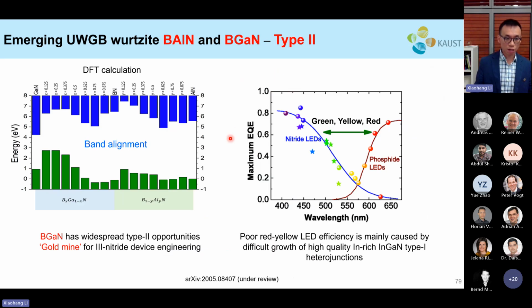So in addition to BAlN, we also look at how BGaN and BAlN with other boron compositions have in terms of the type 2 opportunities. As you can see here, this is the DFT calculation of the band alignment for BAlN and BGaN. This is gallium nitride and this is aluminum nitride, those two are well known, right? But when you add boron into the GaN and AlN, you start to see that the band alignment starts to change pretty dramatically across different compositions, right? This is partially reflected by the bandgap versus lattice constant, which I showed you earlier, right?